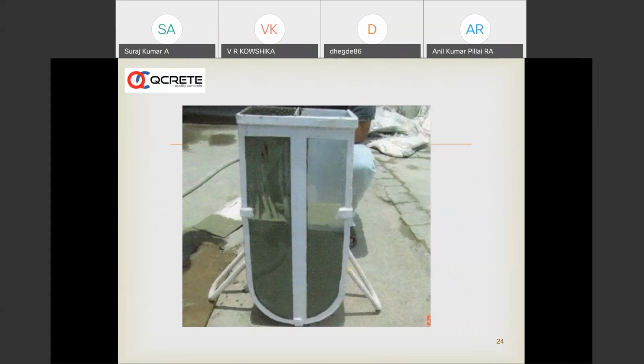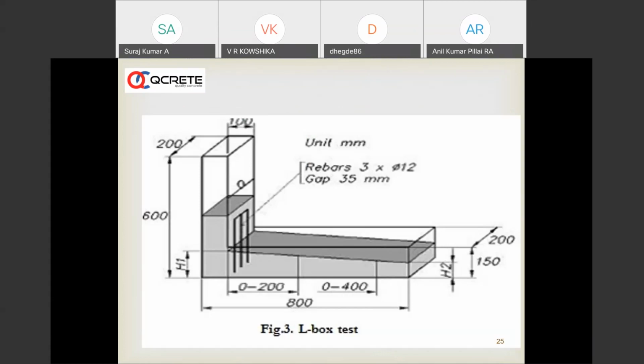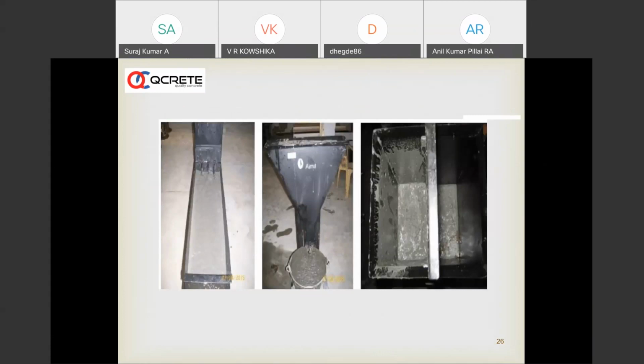And this is a U box test that we do for SCC. L box, which we do for SCC concrete. A V funnel, for example, we place the concrete here in this V funnel, and it has to be collected, and the time for falling and filling into this bucket should be about 6 to 12 seconds. So these are some of the tests that we do on SCC as a quality control.